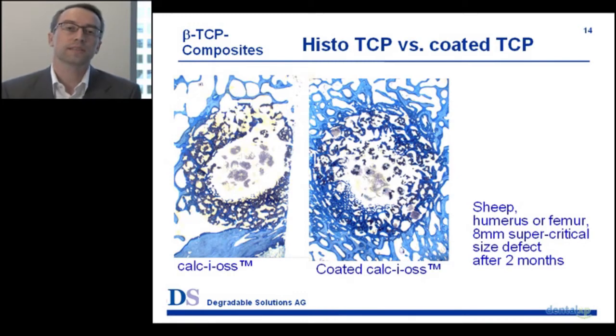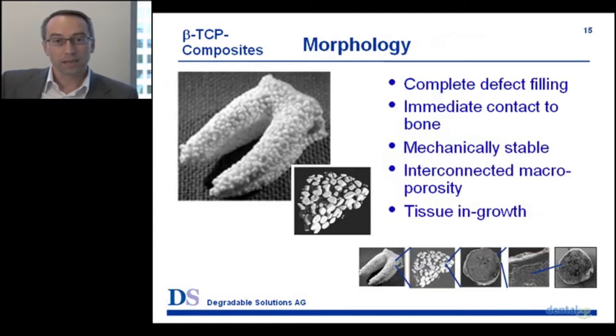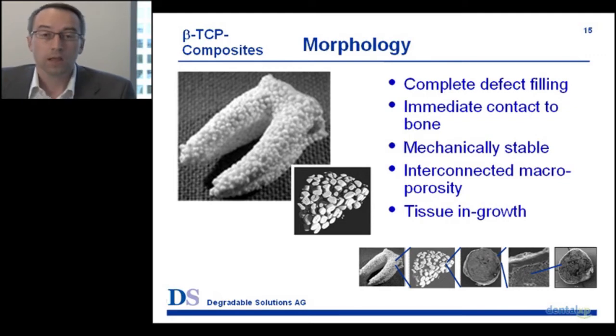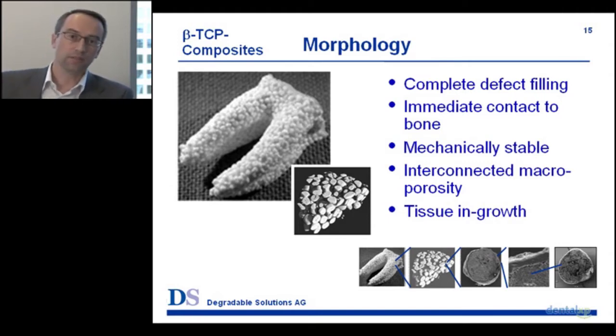Here on the left you see an SEM picture of this biomaterial, and on the right you see a cross section of that, and you can see the porosity available between the granules, which will allow immediate ingrowth of tissue. We measured this porosity, and we have seen that we do have pores of up to 700 microns, with an average pore size of around 200 microns. So tissue is able to grow into a structure like that. We made sure that this biomaterial likes blood, and so as you can see, it can really take up blood. So blood can invade the graft, which is optimal for bone regeneration.